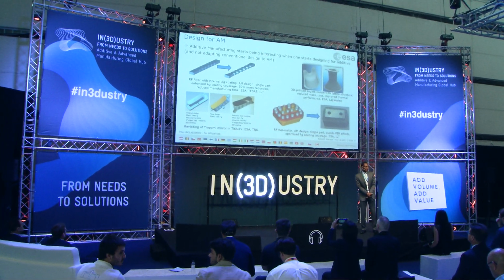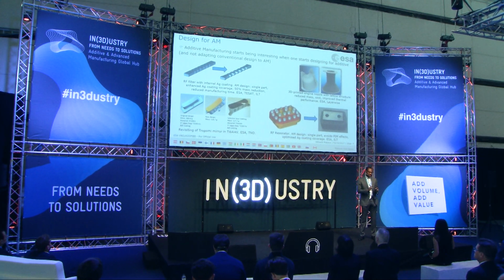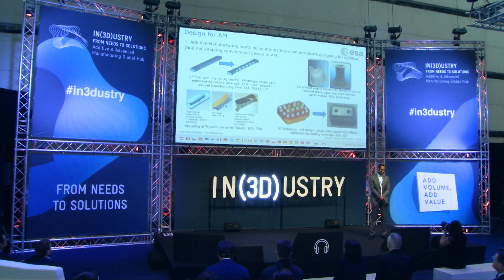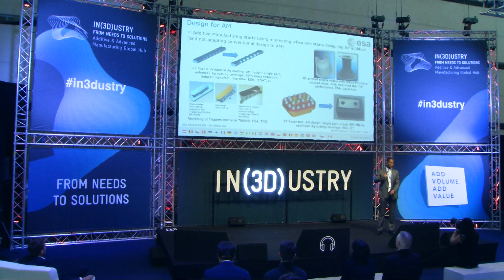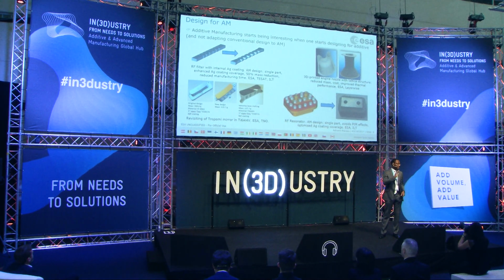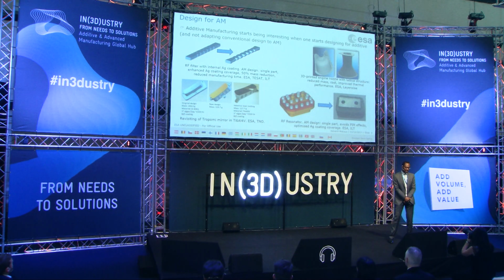On the top left, you have a radio frequency filter where we changed the geometry to curved internal surfaces to optimize the coverage of the internal silver coating, which is used for RF properties. And we also achieved a 50% mass reduction by topology optimization. On the top right is an engine nozzle, and we used a lattice structure on the outside in order to optimize the thermal exchanges and the thermal behavior of the nozzle.